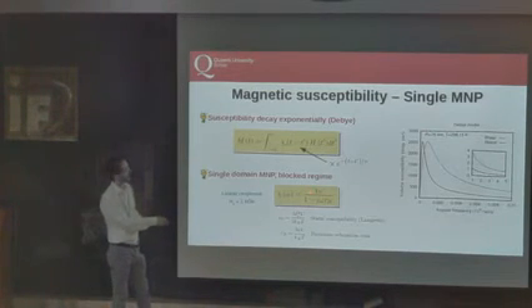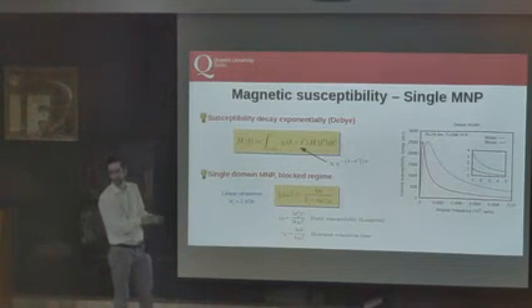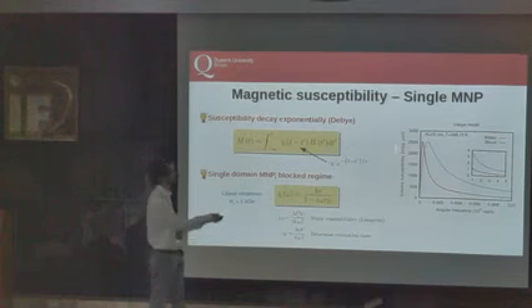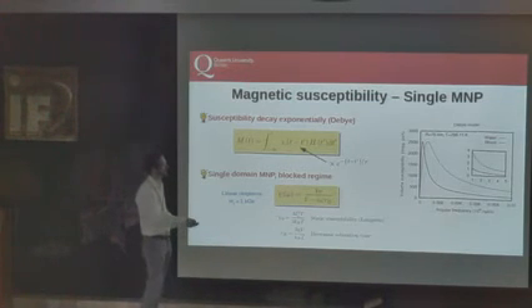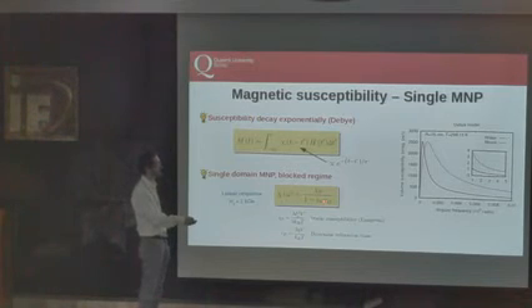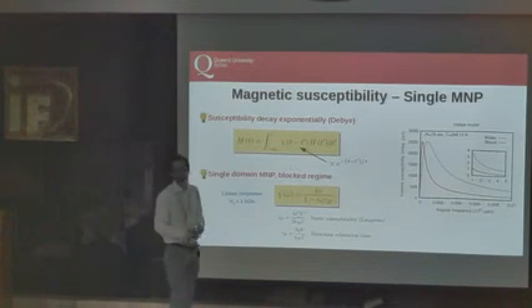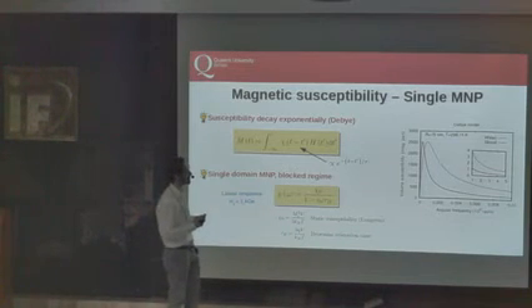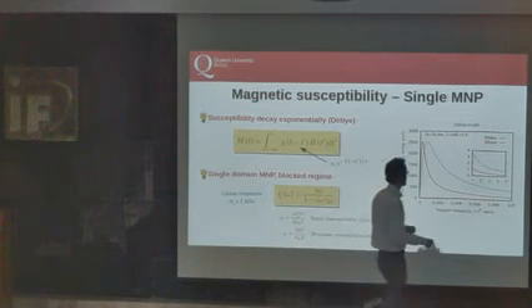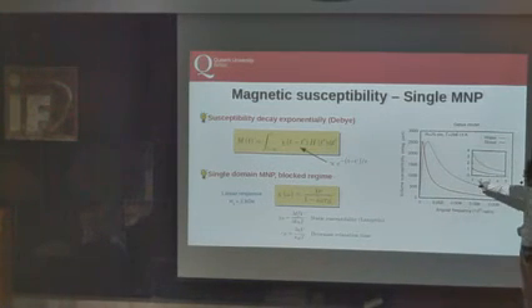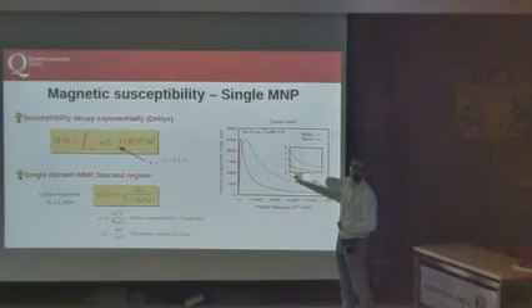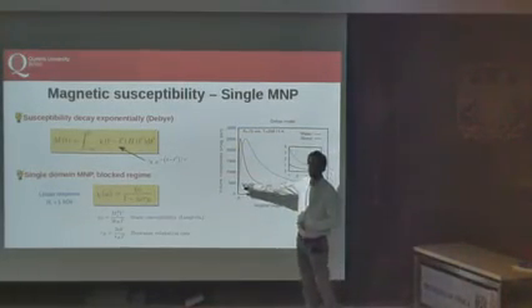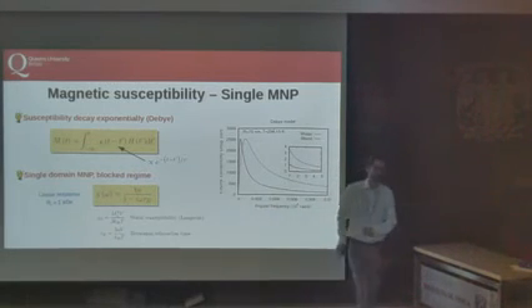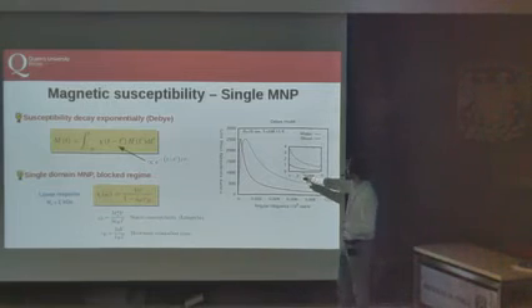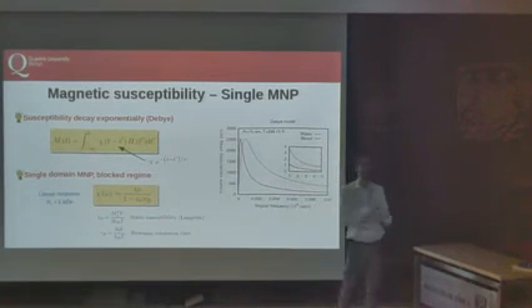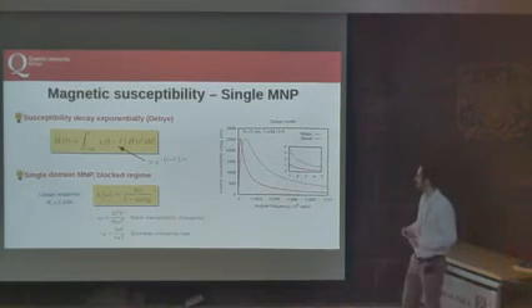Well, you can look at this functional form. This is just the imaginary part, which is the part of the susceptibility related to the absorption. There is a peak. The peak is located at the frequency which is equal to 1 over tau B, the Brownian relaxation time. And clearly the position of the peak depends on the viscosity. In our experiments, I think the equivalent frequency is here. So we are not at all close to the peak. So if I have to apply this to my experiment, I would probably be interested in the tail, not in the peak susceptibility, not in the resonance.